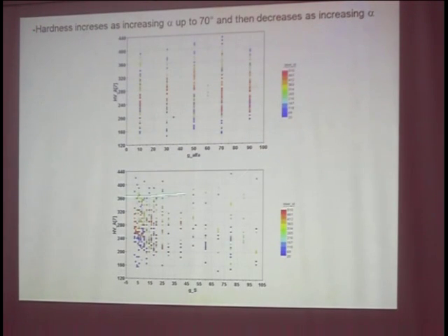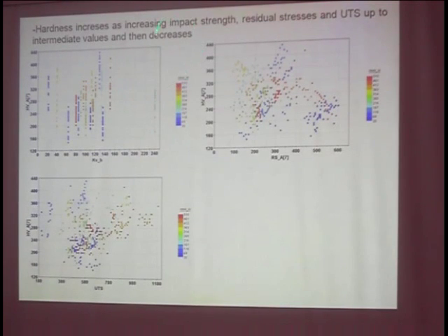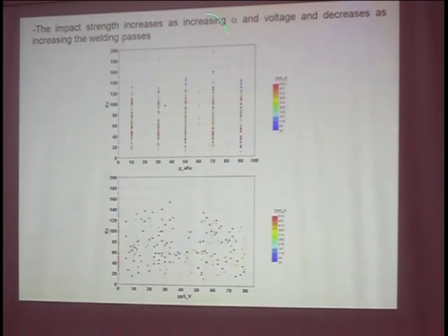And in order to give a general law and a general way to be followed to optimize the welds and the consequent mechanical properties, in particular, we found that hardness increases with the angle of the weld up to 70 degrees and then decreases as the alpha angle increases. Hardness increases as impact strength, residual stresses, and ultimate tensile strength increase, up to intermediate values, and then decreases. For the impact strength, it increases with increasing angle and voltage, and then decreases as the number of welding passes increases.